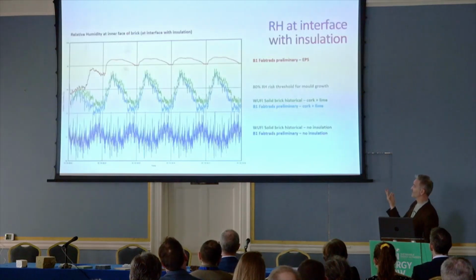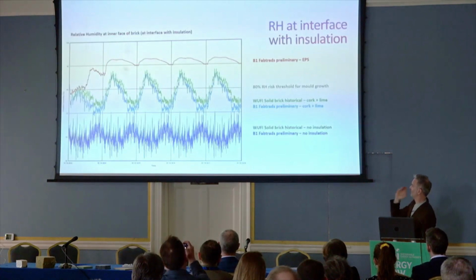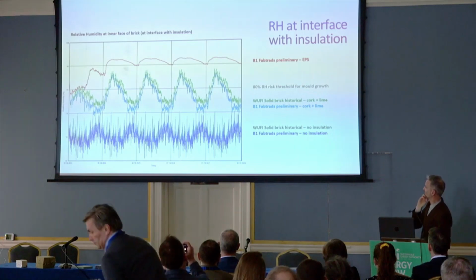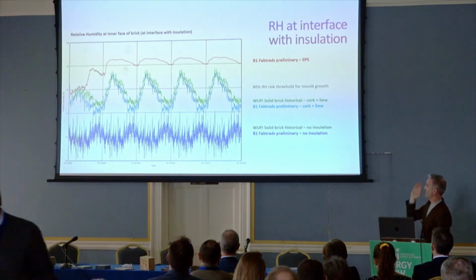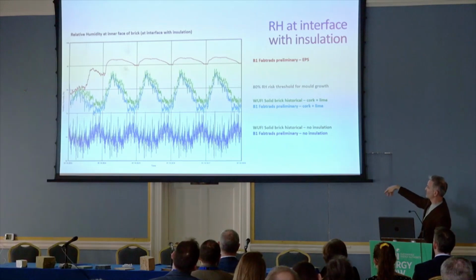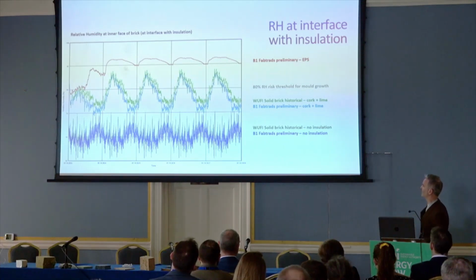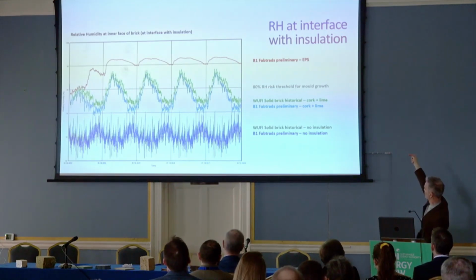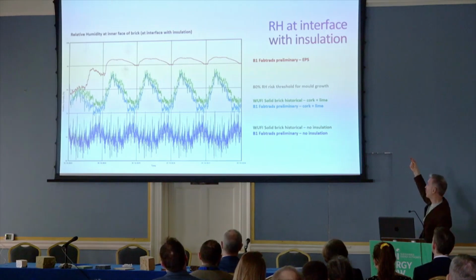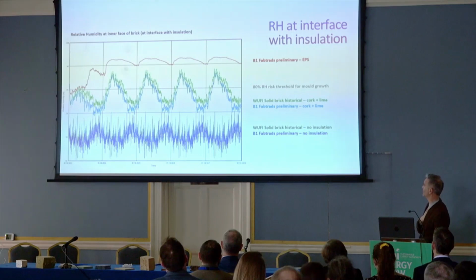This is a multi-year simulation. So ignoring the early stage of the simulation and just looking at where the simulation stabilizes, each line is the 1st of October, so that's the winter and summer peak and trough cycle. There's an 80% line there, the grey line that you might be able to see, corresponding to the 80% RH risk threshold. So the EPS insulated wall is much higher than that, with very dangerous conditions for mold growth.